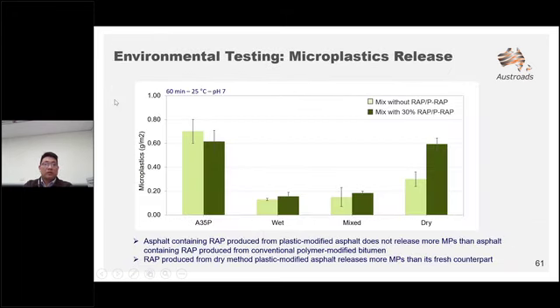In terms of microplastic release, as we can see here, asphalt containing RAP produced from plastic modified asphalt doesn't release more microplastic than the asphalt containing RAP produced from conventional polymer bitumen. And interestingly, we have the RAP produced from the dry method plastic modified asphalt release more microplastic than the fresh one, as we can see here.